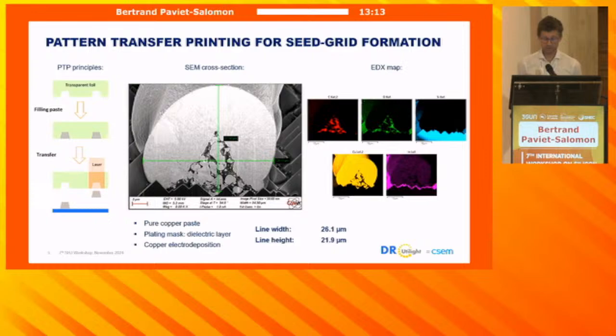So with this approach, we demonstrated already some time ago some nice results. Just to illustrate, I'm sharing with you something we reported already several months ago. It's the plating we realized on heterojunction precursors where the seed grid was deposited using pattern transfer printing. On the left you have the schematics of the PTP. It consists in using a laser beam to transfer the paste onto the precursor. And as you can see on the SEM cross-section picture in the center, we managed to obtain a pretty nice plated finger embedding this very nice copper seed grid. And the aspect ratio is pretty nice because we have a height of 22 micron with a width of 26.